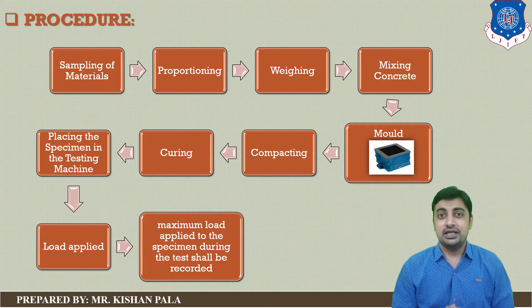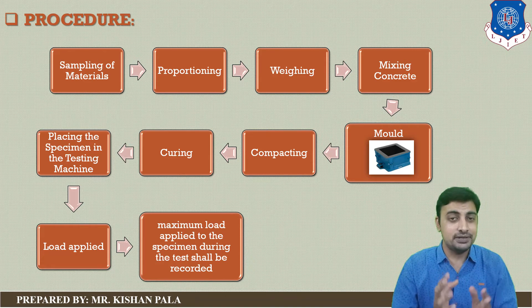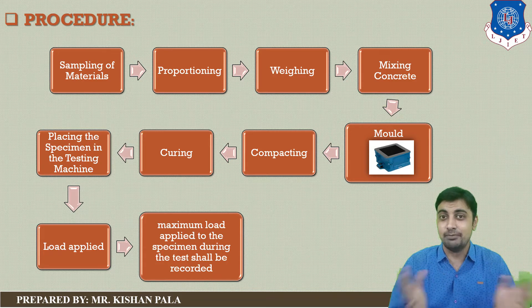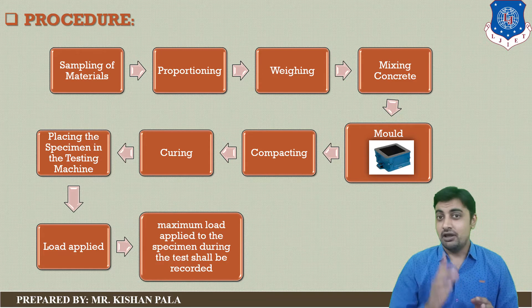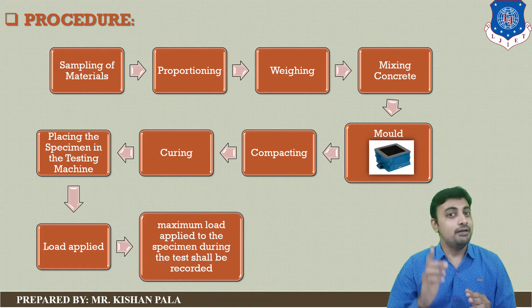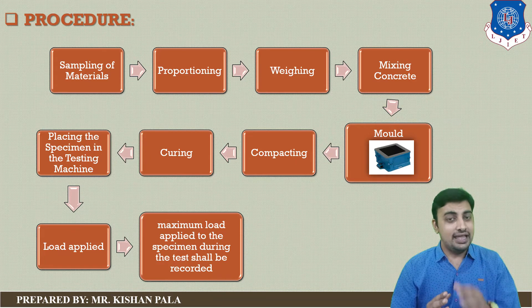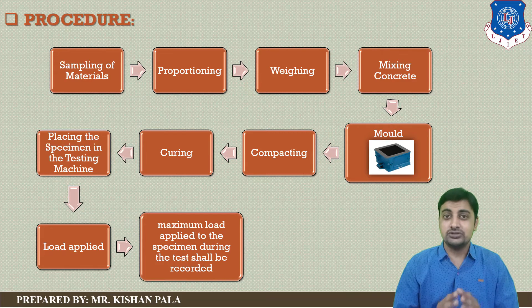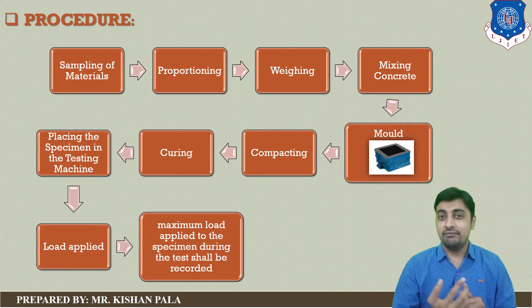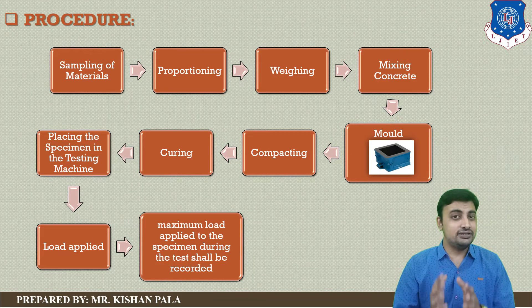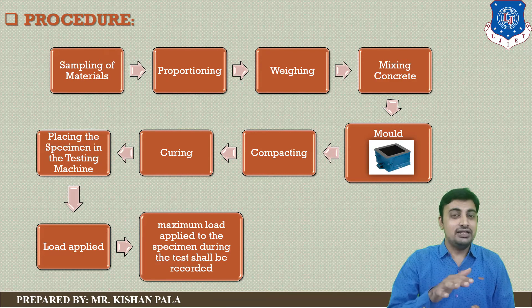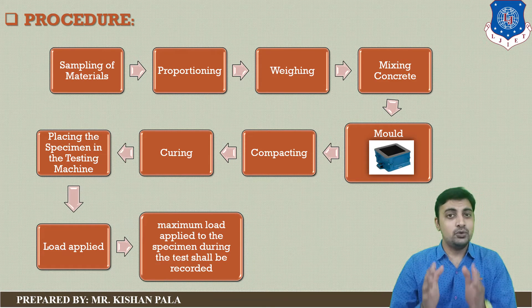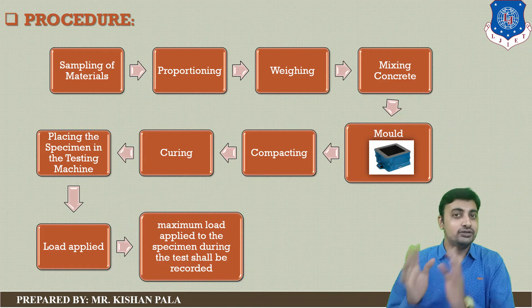After preparing the concrete mix, you have to fill it into the mold. You can see here we are using a cubical cube mold for finding the compressive strength. We can use different sizes and shapes of cube molds; in general, we use 150 mm × 150 mm × 150 mm cubes, or 100 mm × 100 mm × 100 mm cubes for aggregate size less than 20 mm. You can also use a cylindrical specimen with 150 mm diameter and 300 mm height. After placing the concrete mix in the mold, you have to compact it properly and fill it up to the surface.